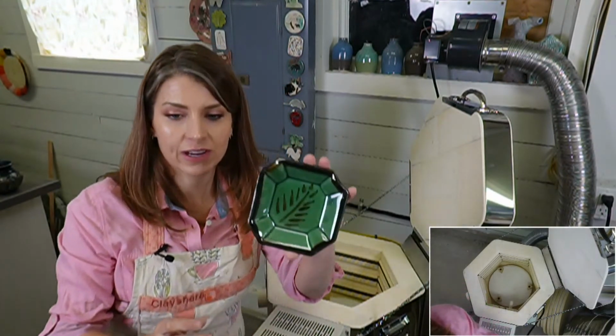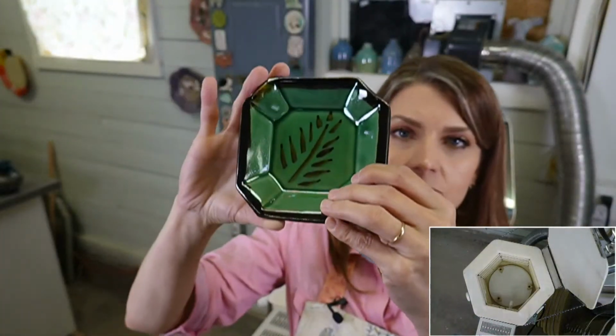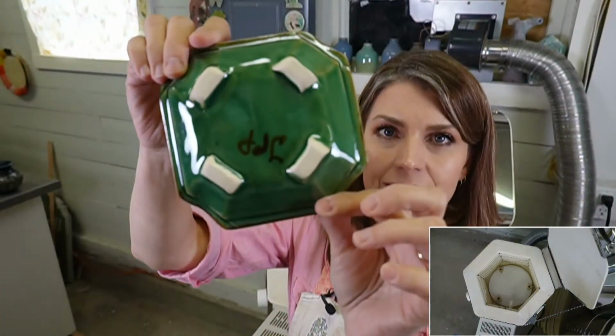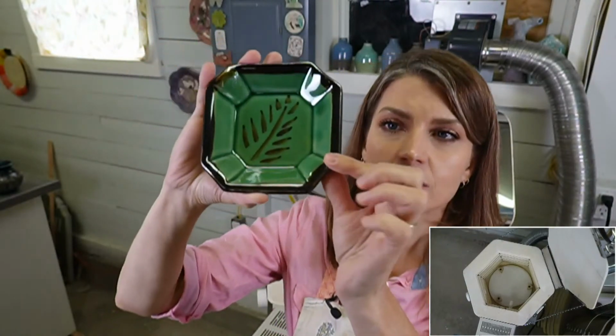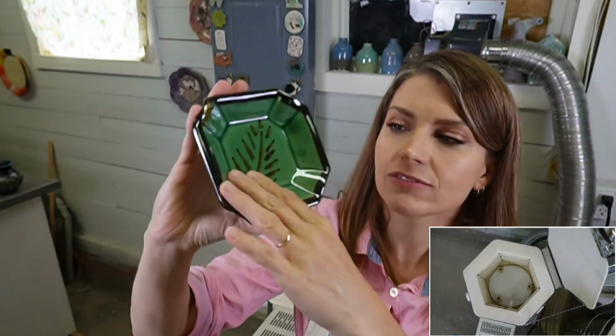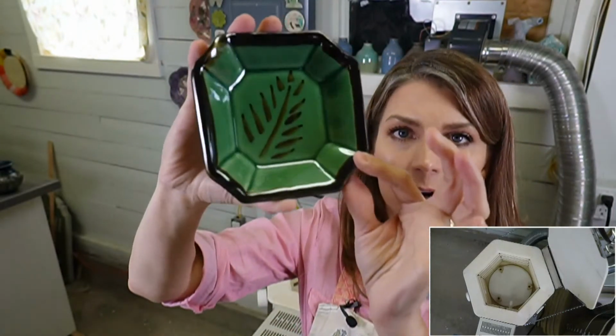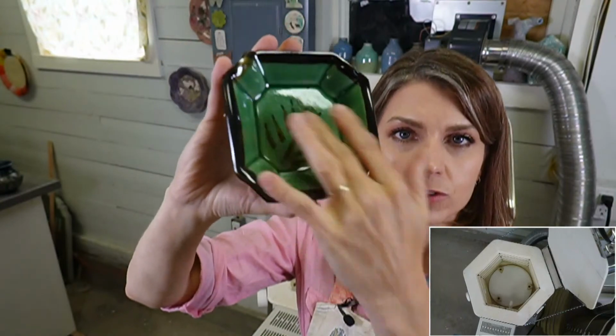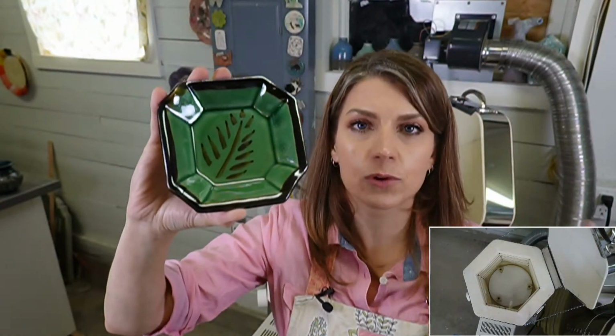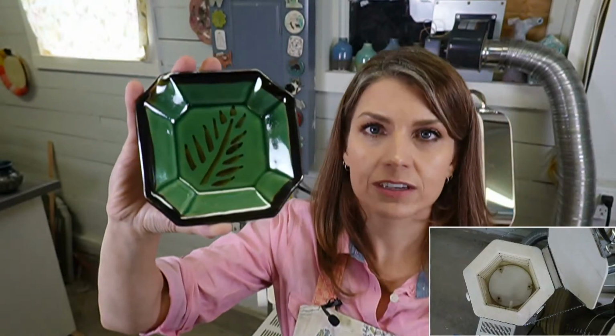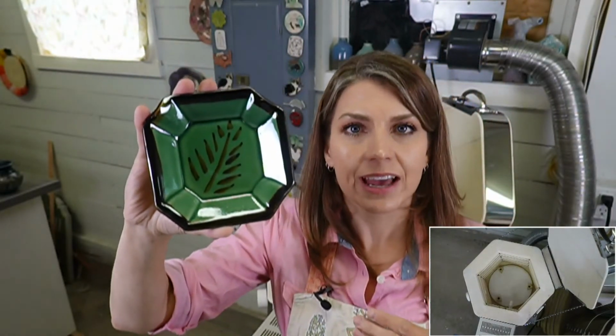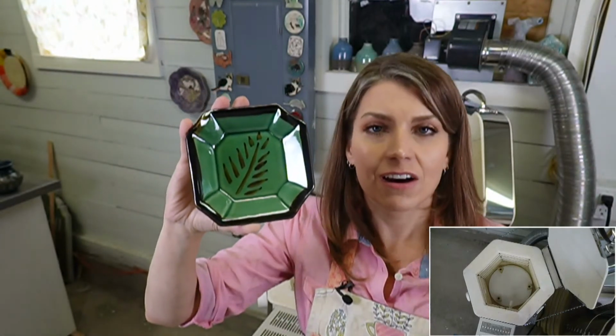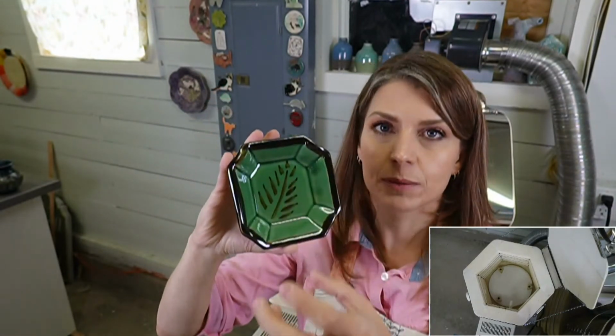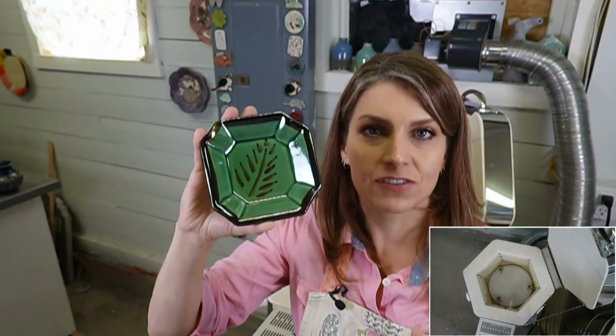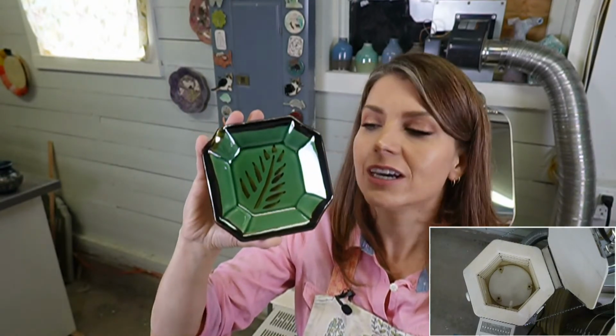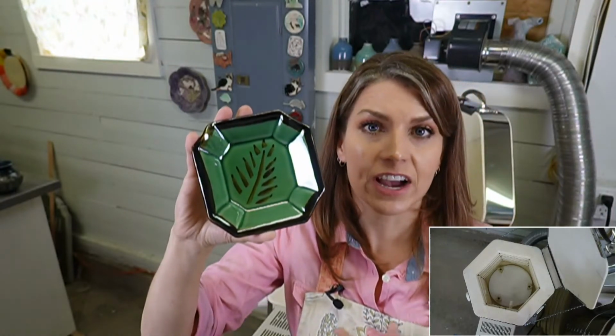All right, so this right here is my Oribe also on B-Mix. And another thing we can talk about is when you're testing out a glaze or using a glaze, you have to look at how it fits. So here we have no pinholing. It melted. We have a beautiful smooth surface. So both my Oribe and my cranberry, cone 5, perfect melt. We have no pinholing. Pinholing can happen when you bisque fire if you don't bisque fire hot enough or long enough. You've got to get those air bubbles out. The clay is off-gassing during bisque firing. You have to let all of that get out and burn out. So this is part of the reason why I do a slow bisque fire too.